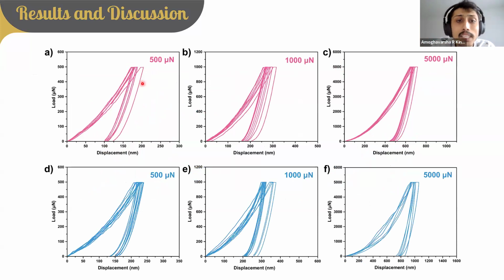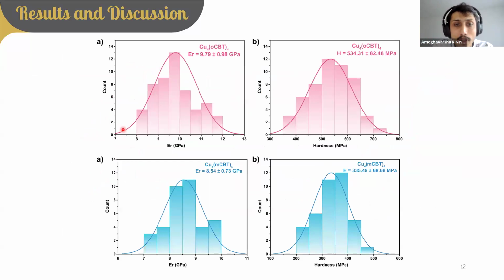From each unloading curve, we extracted the Young's modulus and hardness values, which we plotted as a distribution curve to obtain the Young's modulus and hardness values as shown here. Again, the values are higher for Cu4 OCBT, being 9.79 gigapascal, and 8.54 gigapascal for Cu4 MCBT. The hardness also follows the same trend.